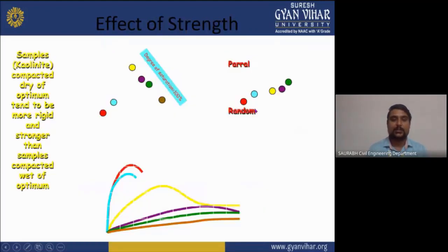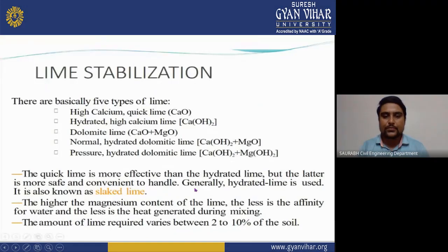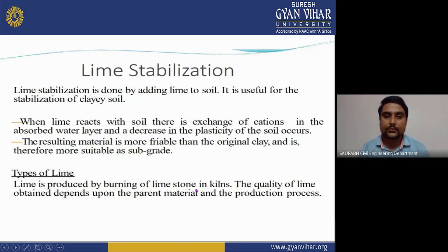Now you can see here what will be the effect on the strength. Samples of kaolinite compacted dry of optimum tend to be more rigid and stronger than samples compacted wet of optimum. Okay, we were on the lime stabilization. The higher the magnesium content of the lime, the less is the affinity for water and the less heat is generated during mixing. The amount of lime required varies between 2 to 10% of dry soil.